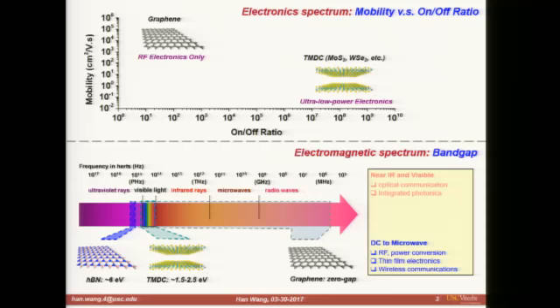We have seen molybdenum disulfide transistors with on-off ratios on the order of 10 to the 8, 10 to the 9, and even 10 to the 10, making them kind of attractive for developing some sort of thin film or flexible electronics applications that can run at very low power consumption, especially in the off state, low power.